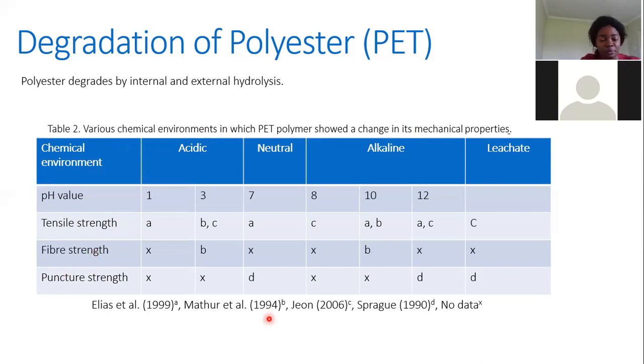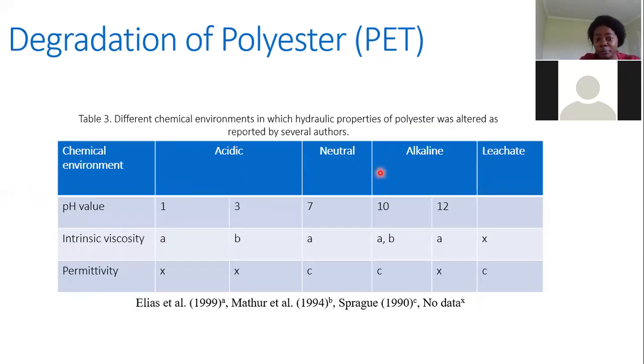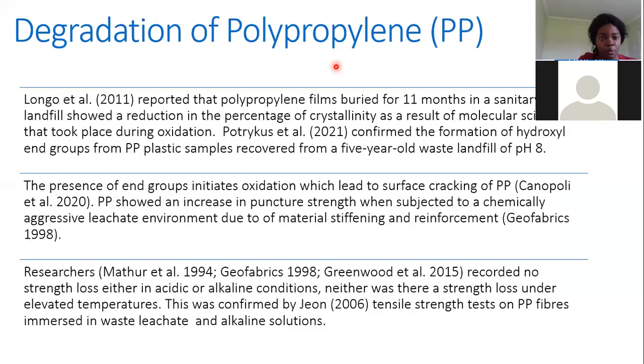And the change that occurs in polyester is not just mechanical change. The hydraulic properties of the polyester were also altered as a result of this chemical action. The intrinsic viscosity and the permittivity of the polyester was also affected. Now, how does polypropylene degrade?